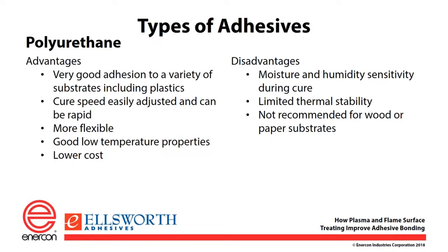A polyurethane is another choice. These offer very good adhesion to plastics and are very commonly used on plastics. They also offer good adhesion to other substrates like metals. The cure speed can easily be adjusted, which offers advantages in application method. They tend to be more flexible, less rigid, so they're frequently a better material for CTE mismatches between substrates. They have good low temperature properties, once again because of the flexibility, and they tend to be lower in cost.